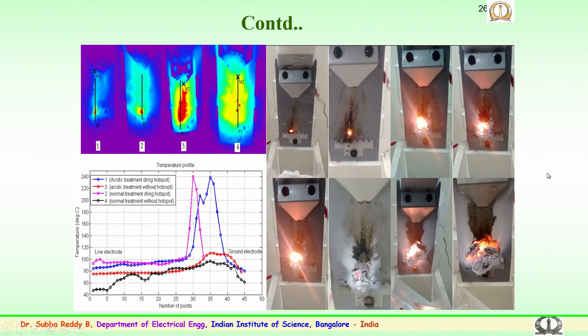This gives the experimental performance for various types of samples. You can see the surface rupture or surface erosion which is happening on the samples at different locations. This is the ground electrode. You can see over a period of time, because of the continuous flow of contaminant, the surface electric stress and the discharges, how the erosion happens near the surface, near the ground end. So, this is a very important experiment which gives the idea of the erosion and the surface degradation happening over a period of time.